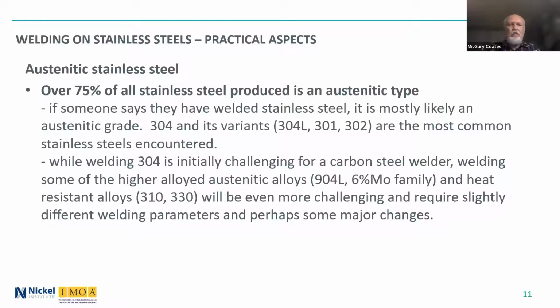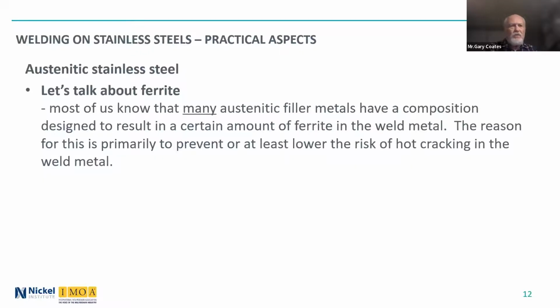And so welding 304 is, of course, as we all know, initially challenging for a carbon steel welder. But when you go to welding some of the higher alloyed austenitic alloys, 904L, the 6-moly family, grades like 254 SMO and AL6XN, and some of the heat-resistant alloys, they're even more challenging, requiring slightly different welding parameters, and in some cases, some major changes over what they do. So just because somebody says I've welded stainless steel doesn't mean that they really know what stainless steel they should be welding. It's up to us to make sure they understand the important differences here.